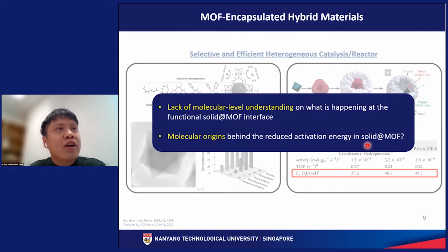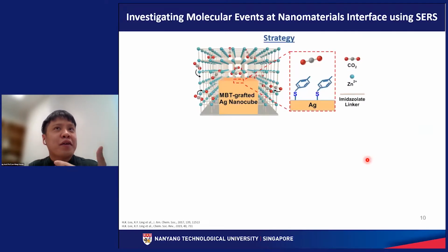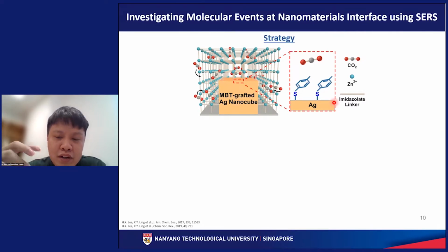However, there is a lack of molecular level understanding of what exactly is happening at the functional solid MOF interface. So what are the molecular origins behind the reduced activation energy in the solid at MOF platform? That is why for my first work, I will discuss how we can investigate the molecular events at the nanomaterial interface using SERS. In this strategy, I embed methyl benzene thiolate grafted silver nanocube with a layer of Metal-Organic Framework. I add methyl benzene thiolate on the surface of silver so that it can serve as a molecular probe to probe the chemical environment right at the solid MOF interface.